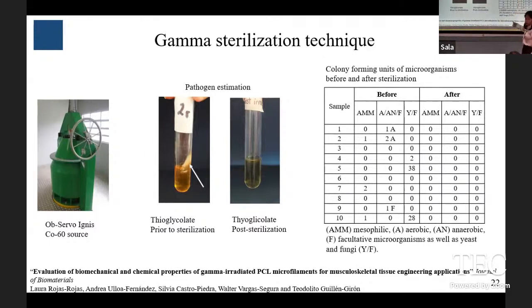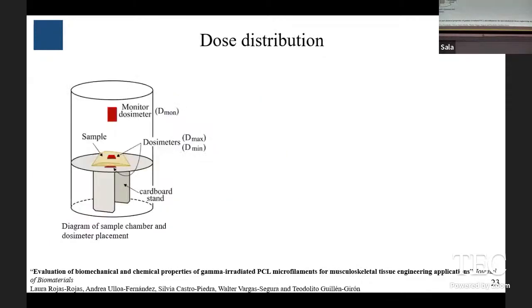And we did that for several samples and also several types of organisms. And as you can see, before and after, they were all clear. So we're certain that our samples were not contaminated. And in addition, this equipment has a sample chamber in which we locate our sample inside a bag. We wanted to be sure if the dose distribution on the sample was working properly.